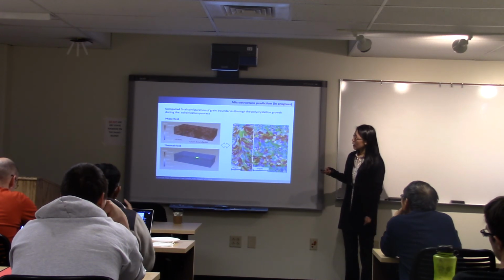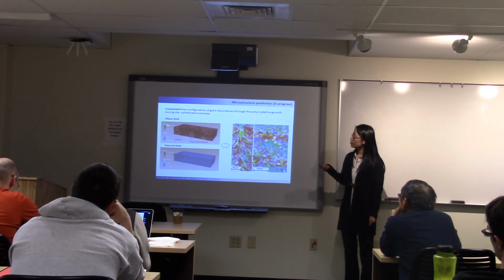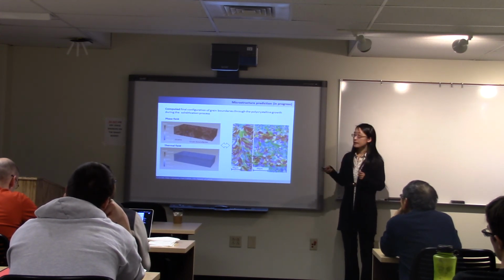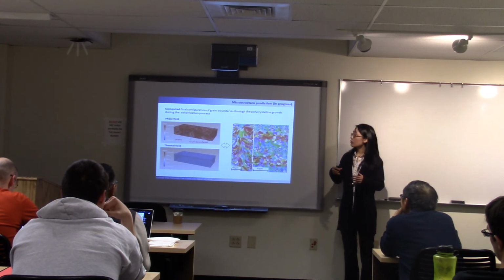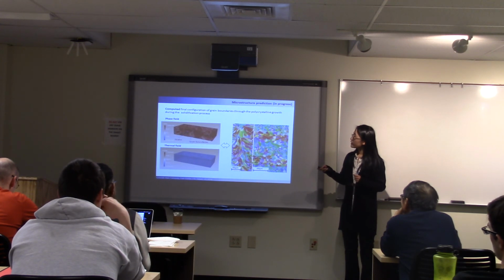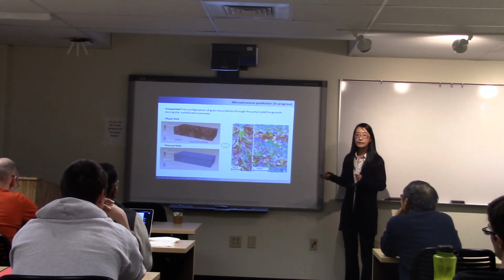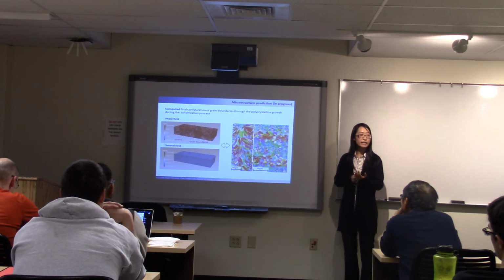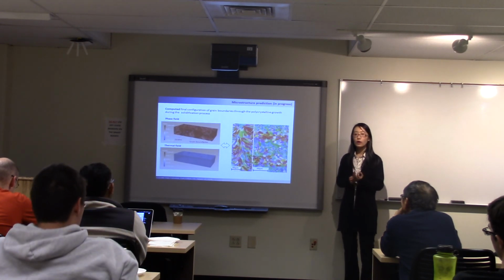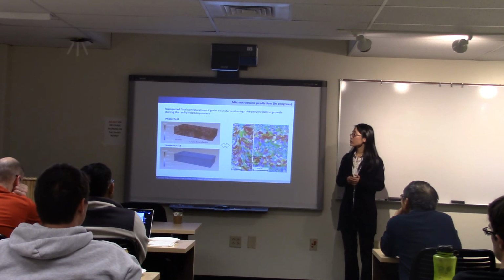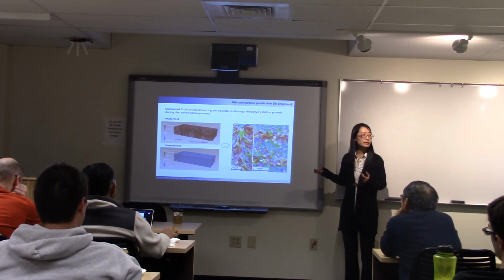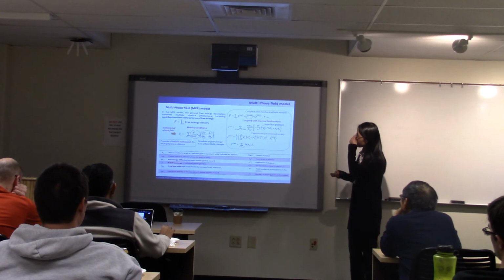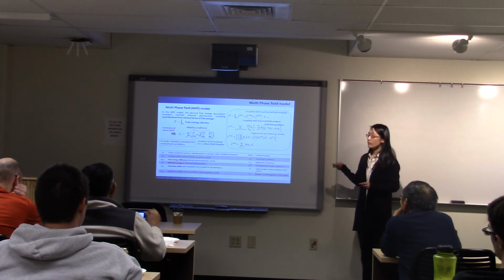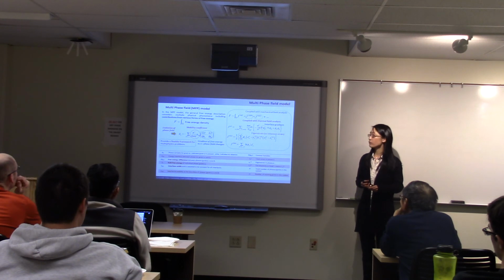So here is another example, where we combined the phase field and thermal field to predict the microstructure evolution. This is during the solidification process and polycrystalline growth. And here is a final figure showing the grains as well as the grain boundaries. We only consider melting and solidification at this point. Further, we also want to add the phase transformation as well as recrystallization to have a direct comparison with the experimental results. So we choose the phase field model because it provides a very flexible framework.